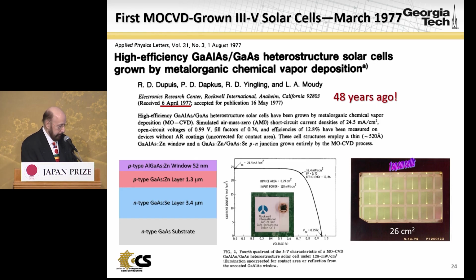And this shows the layer structure. It's a relatively simple three-layer structure: an N-type gallium arsenide selenium doped layer, a P-type gallium arsenide zinc doped layer, and a thin 52 nanometer thick aluminum gallium arsenide wider bandgap zinc doped window layer. This composition was about 20% aluminum in this alloy. In the center panel, you see the performance of this solar cell in the fourth quadrant, showing an efficiency of about 12.8%, air mass 0, which at the time for this type of cell without an AR coating was almost that of the LPE-grown standard cells.